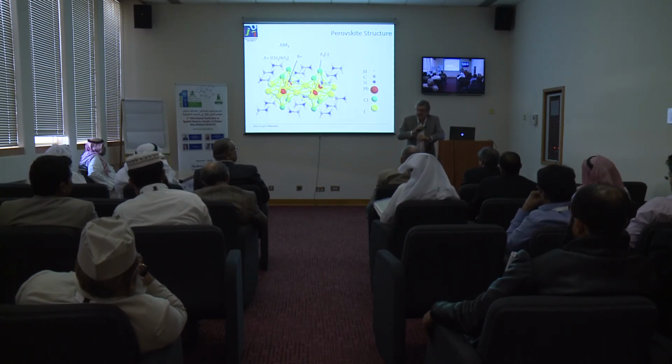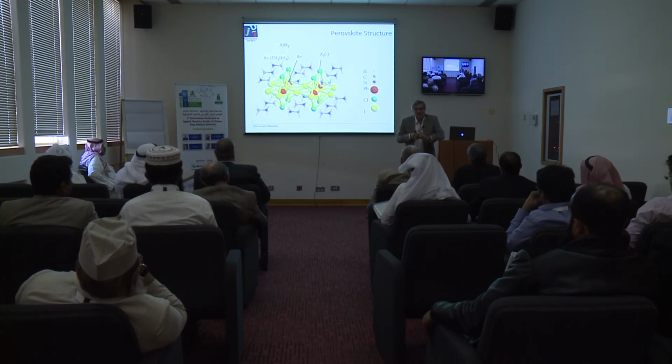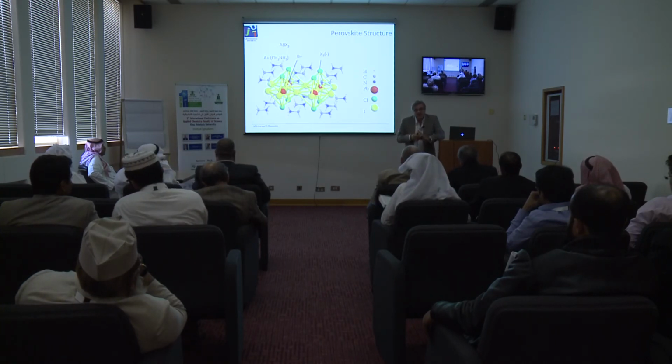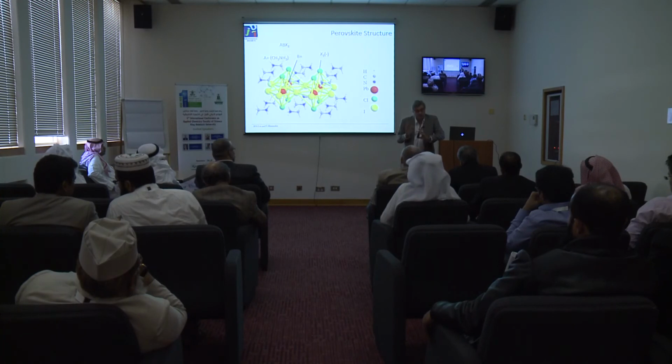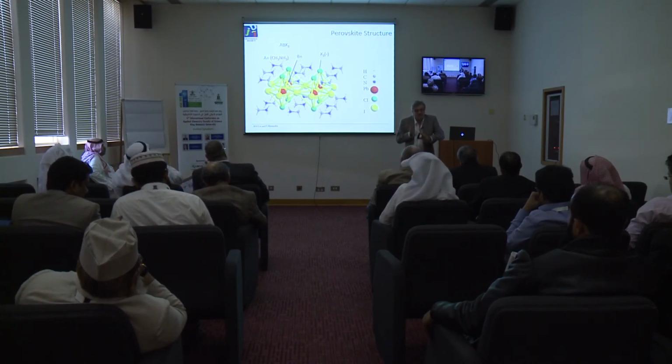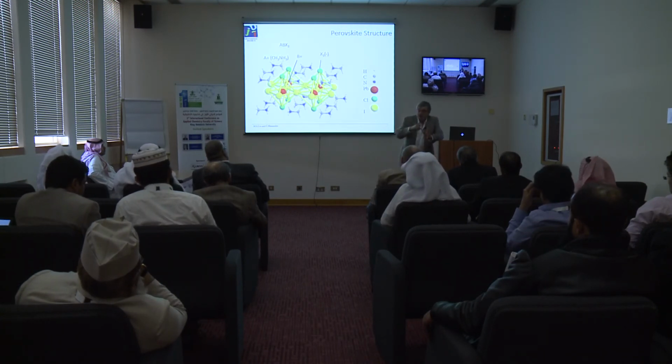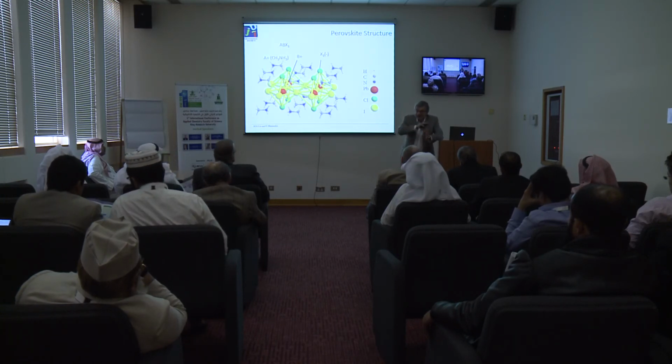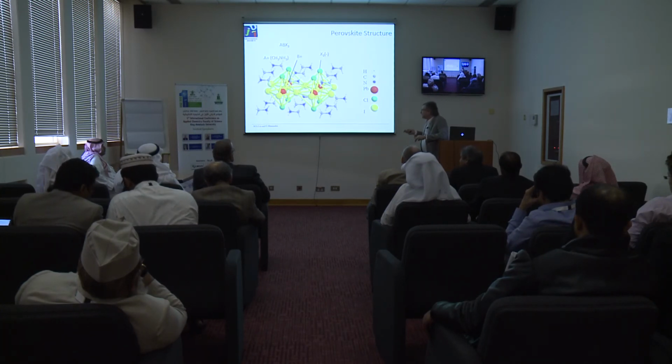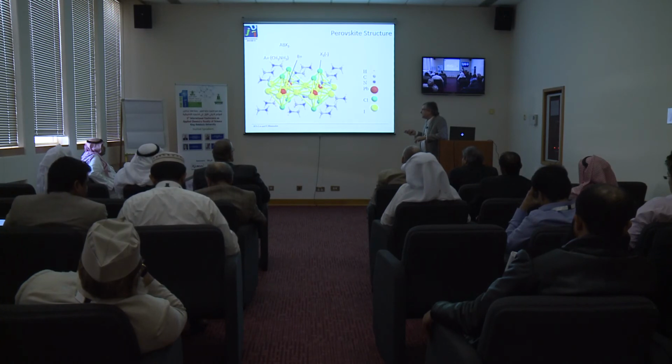It's not easy at all, and nobody has done it, so we don't know what is moving, because nobody has measured partial conductivities. Okay, to measure partial conductivities, you need a special type of contacts. Contacts, for example, that would be selective to iodide and conduct iodide, but not electrons. Okay, but when you put contacts made by iodide, these will react with the perovskite, and that's not good. So it's a big problem, but I announce to you that this structure has peculiar characteristics.